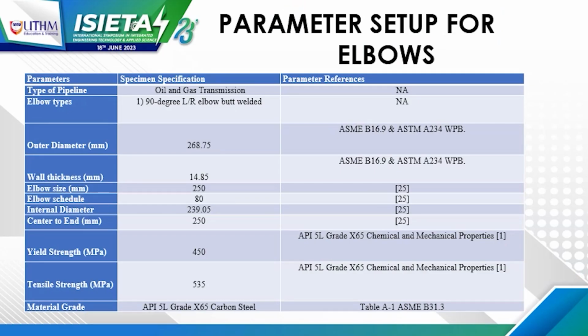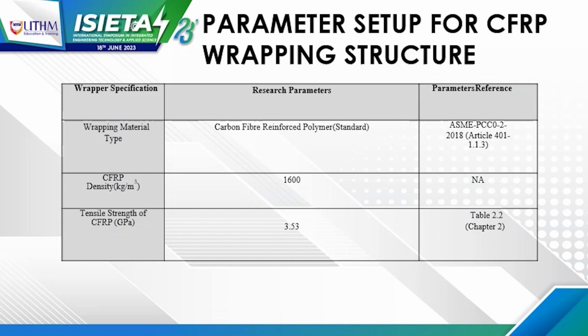So this is the parameter setup for the elbow. The type of pipeline is oil and gas transmission, a 90 degree, 10-inch elbow with the material grade of API 5L grade X65 carbon steel. And this is the parameter setup for the carbon fiber reinforced polymer wrapping structure with 1600 density and 3.53 gigapascal.